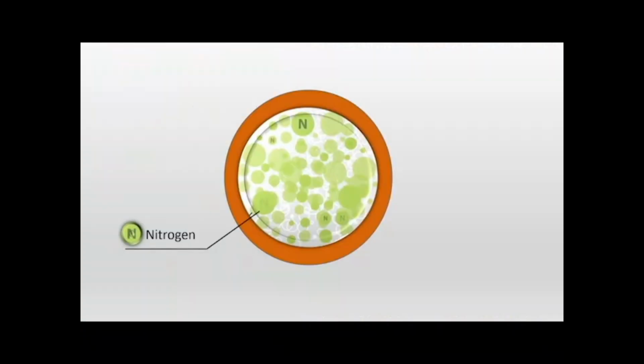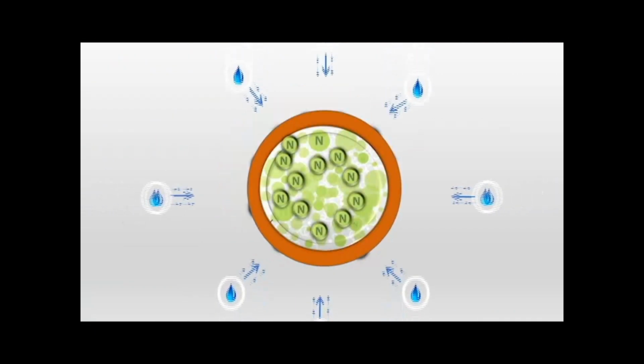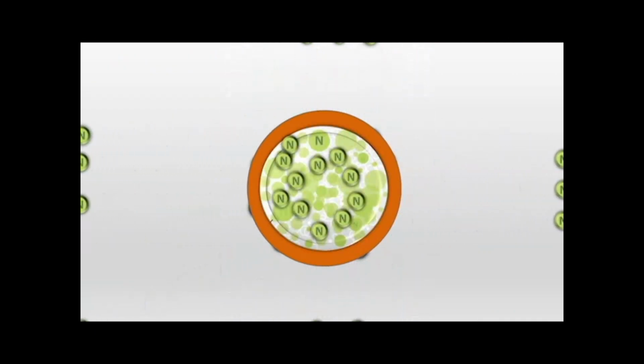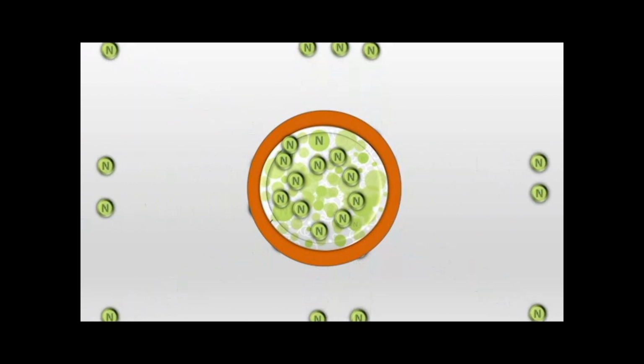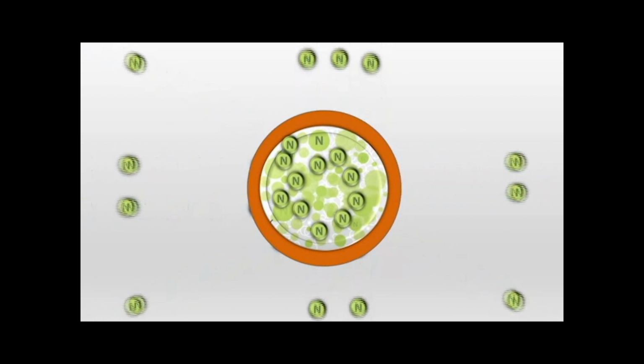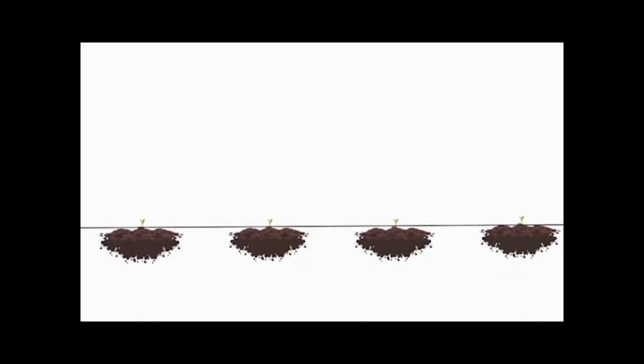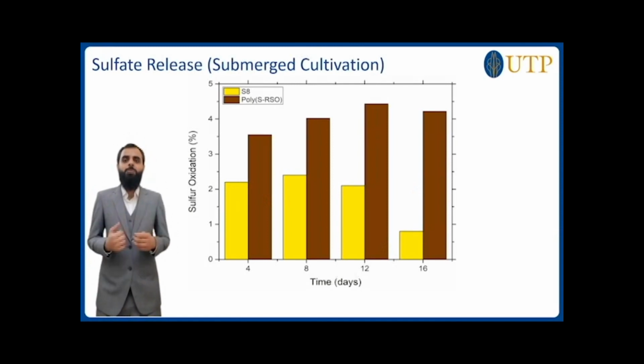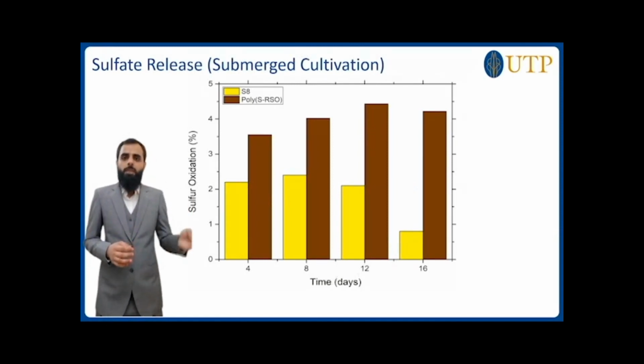Containing nitrogen as a nutrient sealed in a polymer coating, when applied to soil, the water penetrates the pores of the polymer generated by dissolution of surface nutrients, dissolves the nutrient and releases it to the plant. It delays the nutrient release to such a point that its single application is enough for the whole growth process of the plant. The best thing is our produced fertilizer not only delays the release of nitrogen in accordance with the plant nutrient requirement, it also releases sulfate as a secondary nutrient which is required by plants for their growth.